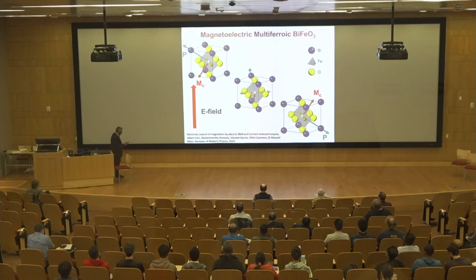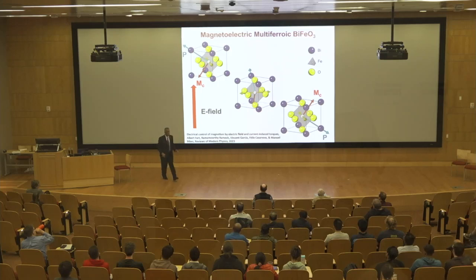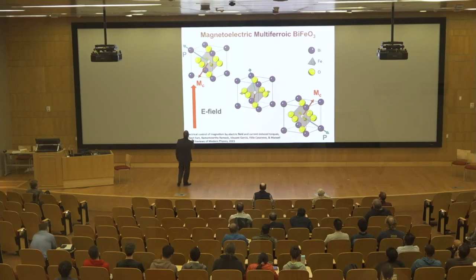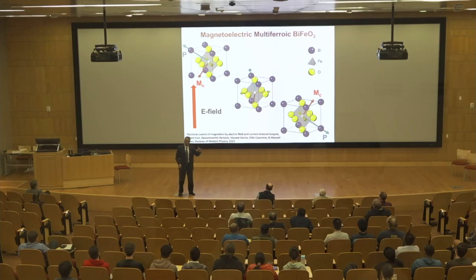When you apply an electric field, the polarization, which is this green vector, switches by 180. For about 10 years, there was a lot of discussion in the field. What happens to the magnetism? That magnetism is MC. I will not go into the details of this MC, but it is a small canted moment that happens because of another quantum mechanical effect called the Dzyaloshinskii-Moriya effect, which is related to spin-orbit coupling in the transition metal ion.